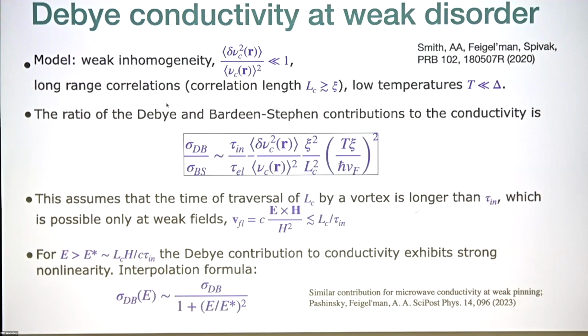So this Debye contribution looks independent of the voltage only if the electric field is sufficiently small. This formula implies that the time of traversal of the correlation radius of the disorder is longer than the inelastic time. And then you get this result. And if the vortices start moving faster, then the inelastic relaxation becomes ineffective. And this nonlinear conductivity falls off as 1 over E squared. And you get, roughly speaking, as a function of this electric field, this kind of Lorentzian form. And the crossover field, where this dependence on the electric field disappears, depends on the correlation radius of disorder and the inelastic time.